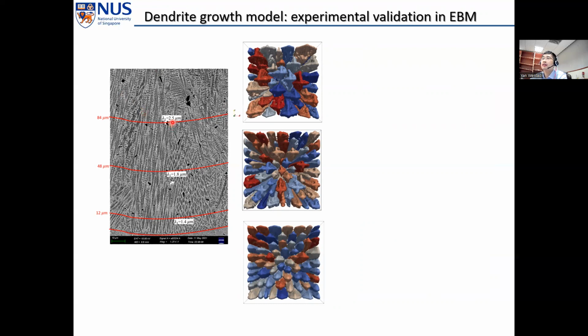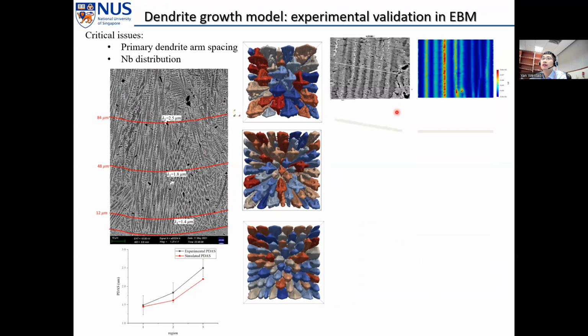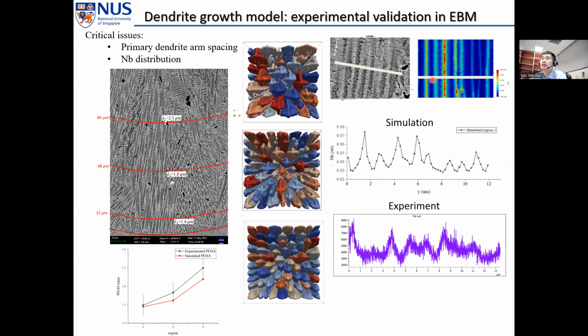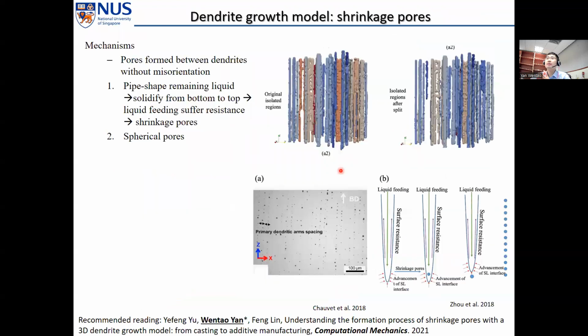So we extract the thermal conditions for the dendrite growth simulation and then validate in terms of the primary dendrite arm spacing and also the solute distribution across the dendrites. So they agree well. And furthermore, based on the dendrite growth model, we can indicate how the shrinkage pores are formed.